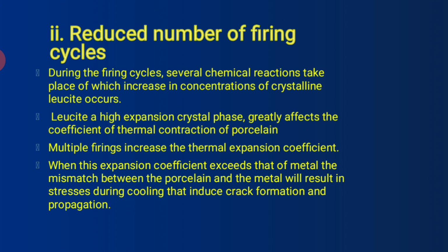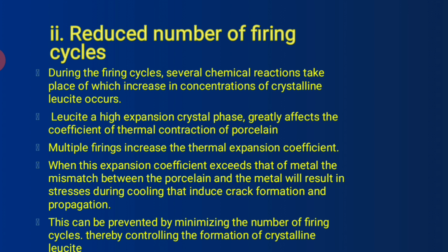Basically, during the firing cycles, several chemical reactions take place which lead to an increase in concentration of leucite, and leucite affects the coefficient of thermal contraction of porcelain. So if there are an increased number of firing cycles, there will be an increased thermal expansion coefficient. And when there is a mismatch between the coefficients of thermal expansion of porcelain and metal, it will ultimately lead to crack formation and propagation. This can be prevented by minimizing the number of firing cycles, thereby controlling the formation of crystalline leucite.